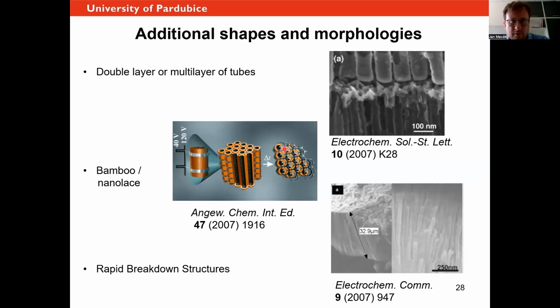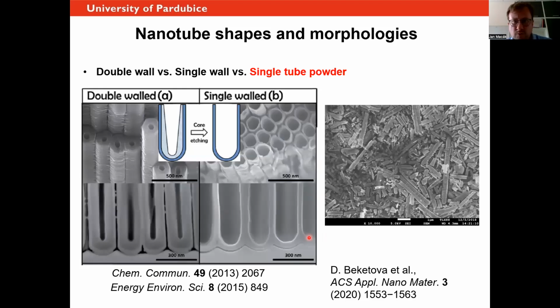You can create double layers, multi-layers. So if you interrupt your anodization and then start again, basically a new layer will be grown. This is what is shown here. You can also modulate the potential, and you can then do some nanolace or bamboo-like structures. You can also do rapid breakdown structures, which are very specific cases of the tubes. Let's look at the most typical tubes that are grown in ethylene glycol.